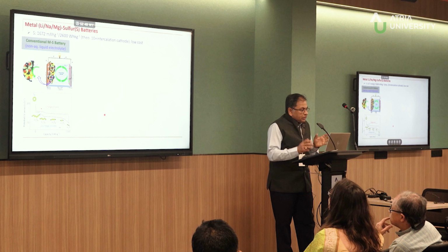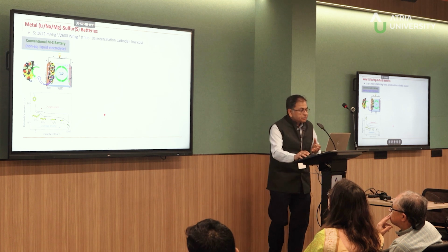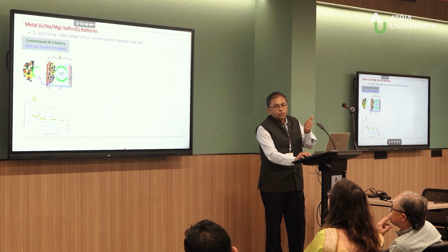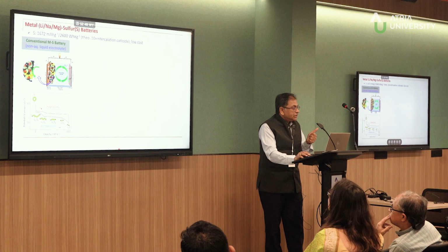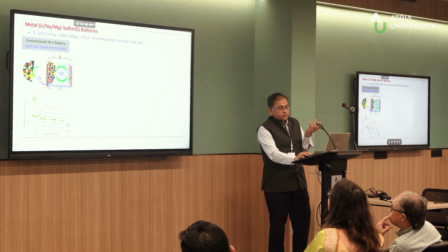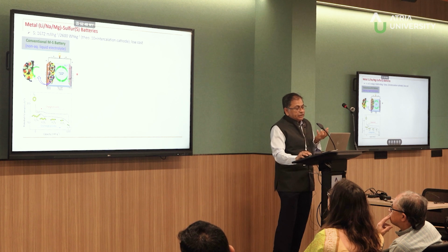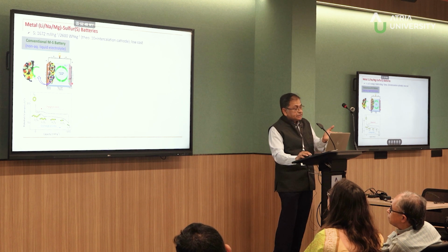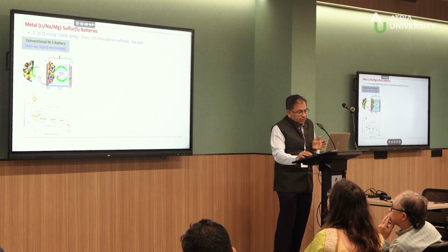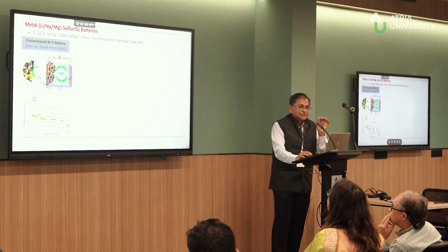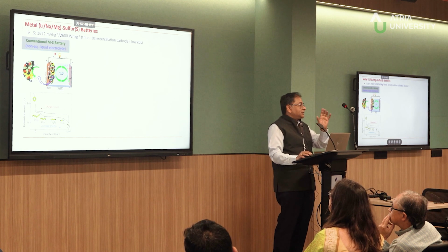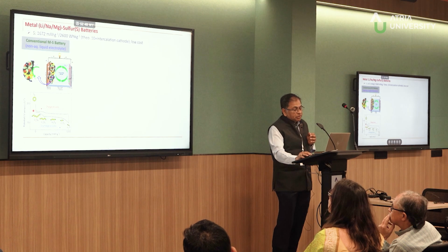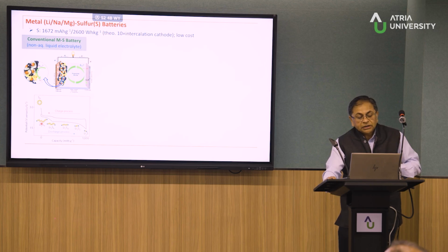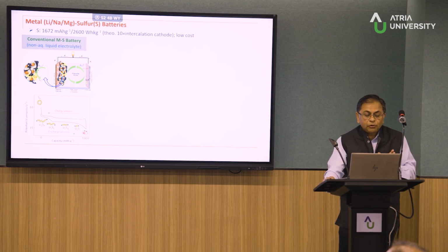All right. So the way the conventional metal sulfur battery works is that sulfur is very good in storage, but it's a very poor conducting system, neither electronically nor ionically. So it is always housed inside a host. Most of the time it is carbon. And it is separated from the metal anode, in this case lithium, by a liquid electrolyte. Now, since this is not an S2 or an S system, this is an S8, the puckered ring of sulfur, it's not a direct conversion. So when you're discharging the battery, it passes through all these steps. You have these higher order polysulfides, then lower, and finally you form, if at all the kinetics is favorable, metal sulfide.